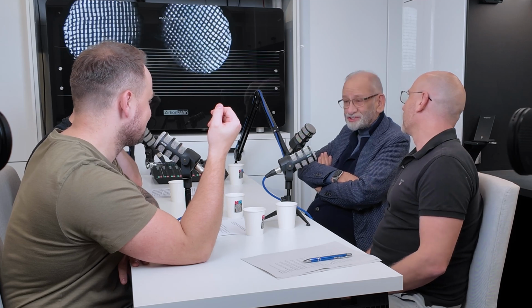Okay, so it's true that they behave differently in the sintering furnace? Yes, a little bit, just a little bit. Because the composition is different, you know. If there is more yttria in it, this is a different recipe, and of course the expansion and the shrinkage are a little bit different, but just a little bit. So it doesn't affect the result. It doesn't affect the result so much, but if you go under the microscope to see the real detail, then you can say the Prettau 2 is even more precise than the Prettau 3, but the impression isn't precise enough that it makes sense to do it impeccably from the laboratory side.